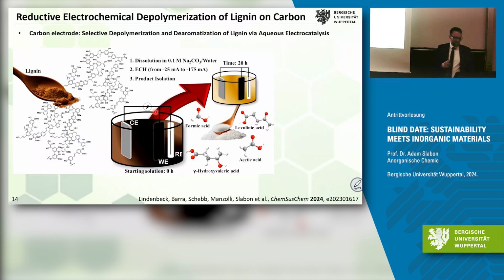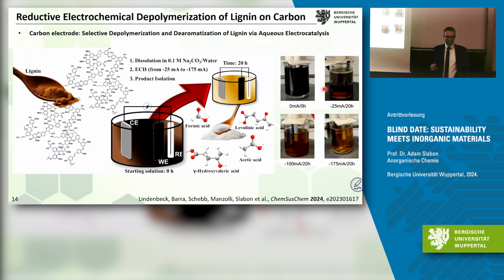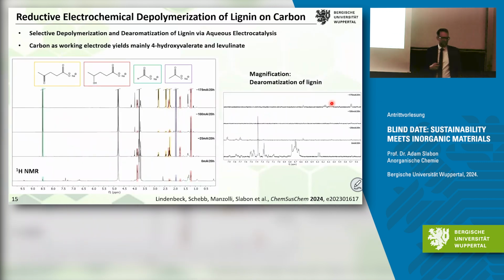And what we got was the same electrolyte in water, but we got as well a color change. So we applied different constant currents and we analyzed the outcome of the reaction. We were quite surprised because we expected aromatics, but to be honest, we didn't see them at all.